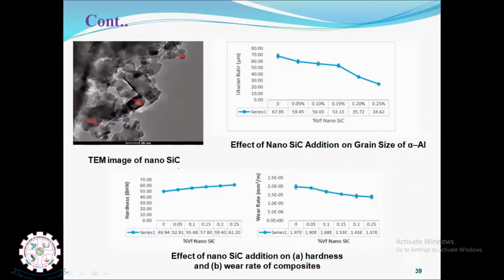So these are the TEM image of the nano silicon carbide particles. They observed that grain size is reduced when they added the nanoparticles into the aluminum, hardness increases, and wear is reduced. That means wear resistance increases. So when they added nano silicon particles into the aluminum, it affects the wear properties, hardness, and grain size also.